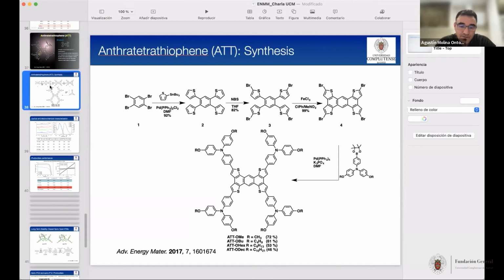The chain affects the film forming ability. When we have shorter alkyl chains, it is very difficult to dissolve. So we need to heat the molecule to 100 degrees and deposit on a device that is also heated at 100 degrees, because if not, it will precipitate very fast. But doing that, we can get very nice and smooth films of ATT with methoxy. On the other hand, when we introduce longer alkyl chains, the problem is also preparing a good, smooth film, but it also comes from the thermal properties of the molecule. Because when you have a decyl group, you are not getting just one glass transition. You are getting four different glass transitions, and not at 100 or 120 degrees, but at 50 degrees. So this will affect the final performance of the device.